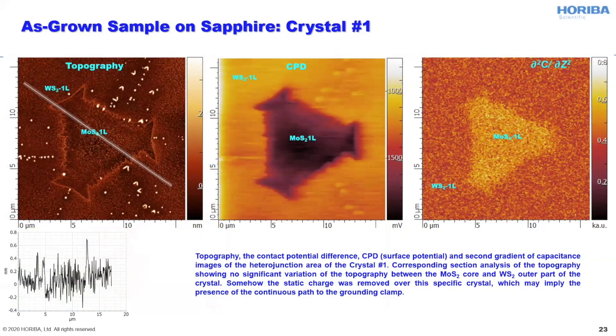So when we took the AFM image, luckily we managed to find a location where the charging of the underlying sapphire crystal was not very significant. So the topography looked normal, very flat, and almost no variation in terms of height between the molybdenum disulfide core and tungsten disulfide shell. But in the surface potential image and in the capacitance image, we could clearly see the difference between the two different materials.